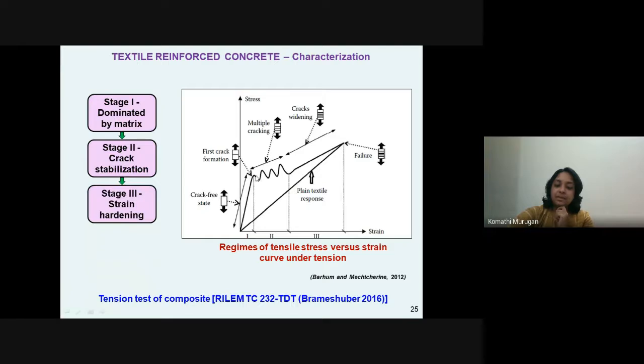Then from this it moves on to the second stage, where the cracks stabilize. That is, there is a formation of multiple cracks over the stretch of the panel. So this stage is called the crack stabilization stage, where multiple cracks get formed, and at a point of time they get stabilized as well. They stop forming in the matrix.